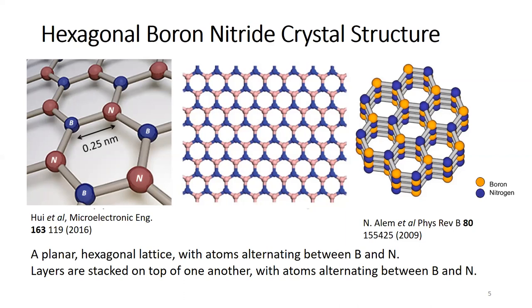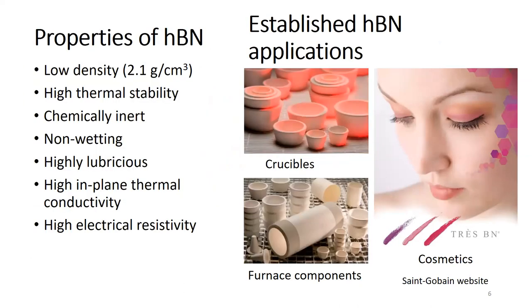And that's more or less what it looks like. So hexagonal boron nitride has been around for 60 or 70 years. It has many advantageous properties: low density, very high thermal stability, and it doesn't oxidize up to 800 degrees Celsius or more. It's chemically inert, so no acids or bases will attack it at room temperature. It's non-wetting and highly lubricious, so it's used in makeup and cosmetics.